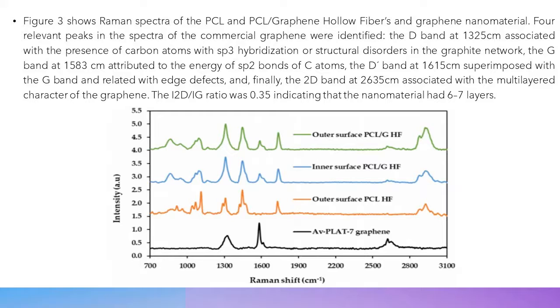The D' band at 1,615 cm⁻¹ superimposed with the G band and related with the edge defects, and finally the 2D band at 2,635 cm⁻¹ associated with the multi-layered character of the graphene. The I2D/IG ratio was 0.35, indicating that the nanomaterial had 6 to 7 layers, as you can observe here in the table.